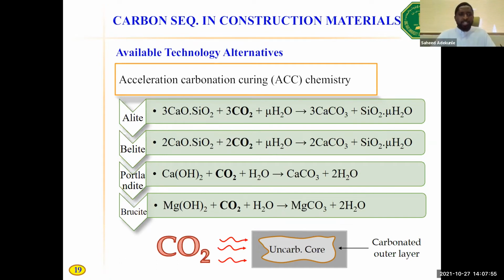And how does this ACC work? You can see below on that slide that when you pump CO2 into a young concrete, the outer layer actually absorbs CO2 and the carbonate is formed in the outer layer. This carbonate precipitates in the microscopic and nanoscopic pores of concrete to give that concrete element an outer shell, which is very dense and much higher quality as compared to the inner core of the concrete member.